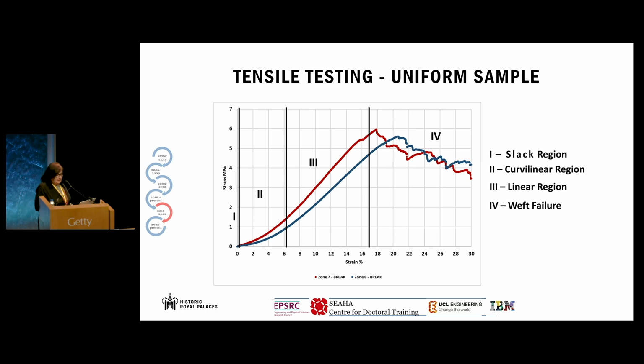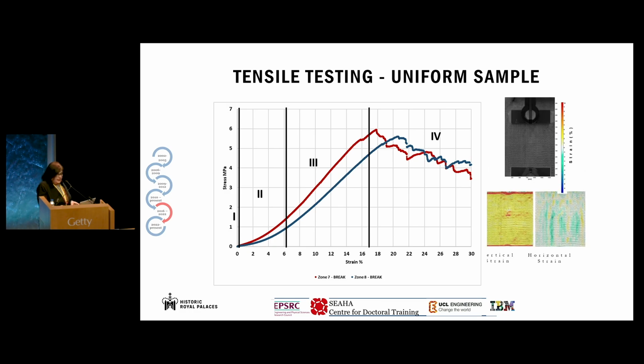Pedro initially tested a uniform wool sample to failure, so that was a historic sample. And here you can see the stress-strain curves of 2 different sample areas from these fragments and their characteristics. The DIC measurements calculated during the experiment show that when the sample is under strain, under tension, strain in the vertical direction, which is the bottom left image, is positive as the fabric is stretching, while the horizontal, the image on the right, is mostly negative due to shrinkage.